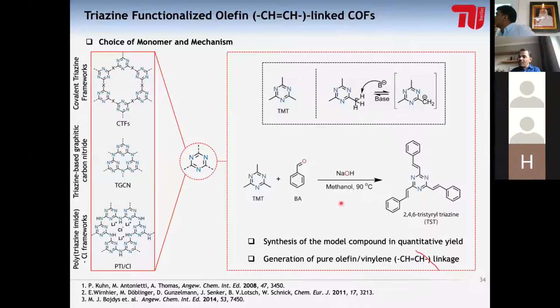To confirm that, we reacted this trimethyl triazine with benzaldehyde, using methanol as a solvent and NaOH as the catalyst. And what we found is that we can get this kind of molecule. What happens in general in the presence of base is that one of the protons can be abstracted by the base, forming a carbanion. And this carbanion starts reacting with the benzaldehyde. This is a typical aldol condensation reaction in the presence of base or acid.